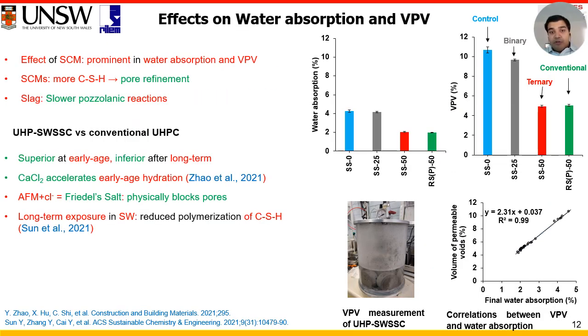Next, moving on to the transport properties, we have found that the effects of SCMs were prominent in water absorption and volume of permeable void tests. As SCMs produce more CSH, which means more refinement to the pore structure. However, it was also found that use of only slag does not significantly enhance the transport properties, probably because of their slower pozzolanic reactions.